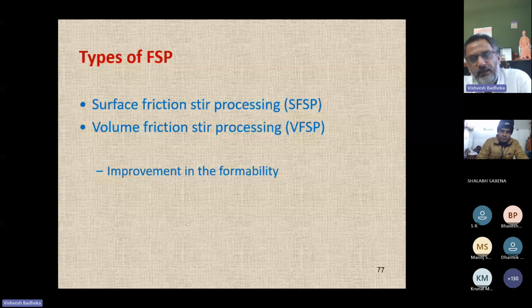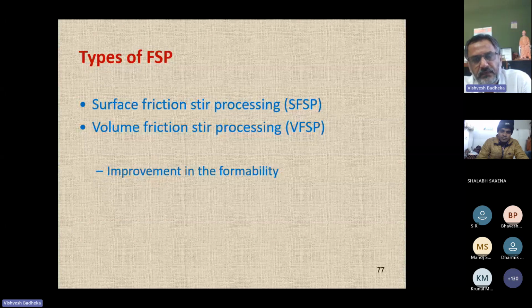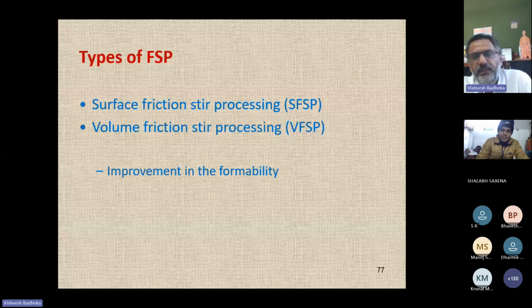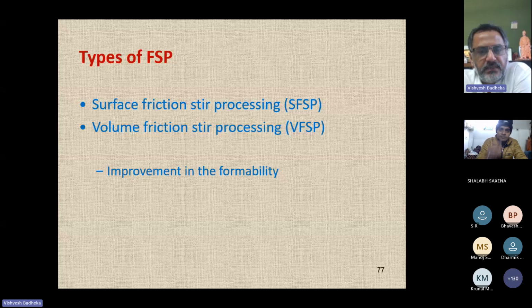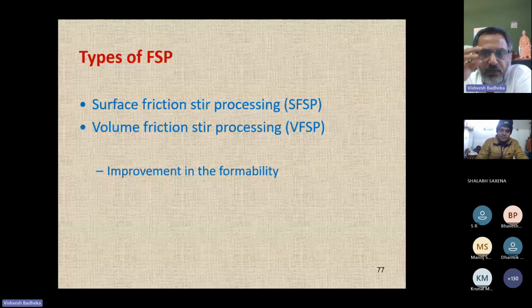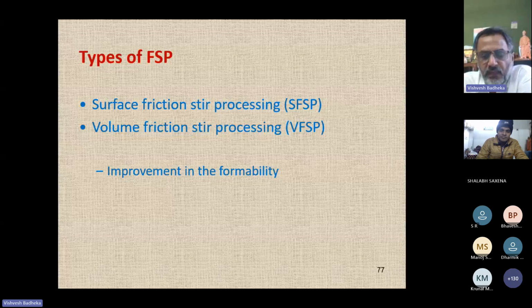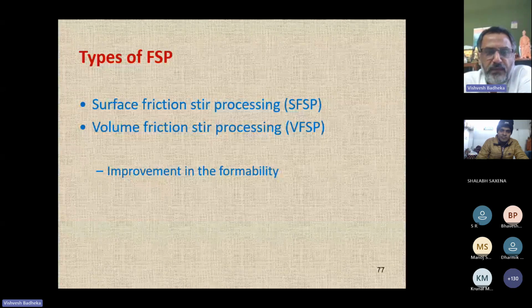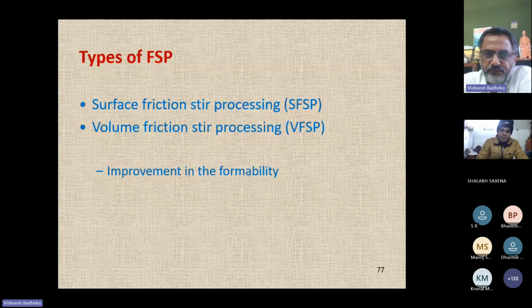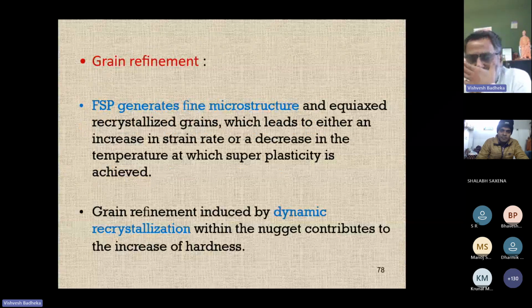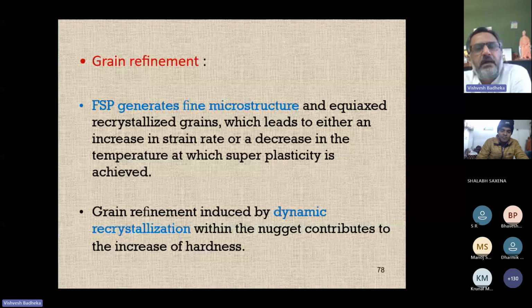If the length of the pin exactly matches the thickness of the plate, you can say it is volume FSP. And if you are doing it only on the surface, just 1 or 2 to 3 millimeter from the surface, it is surface FSP. So depending on the length of the pin, it has been termed as surface FSP and volume FSP. Depending on your need, right? You can do surface FSP and volume FSP, and this will help you to improve the formability behavior of the metallic material. So the mechanism I have already explained to you, the first, which is the grain refinement.